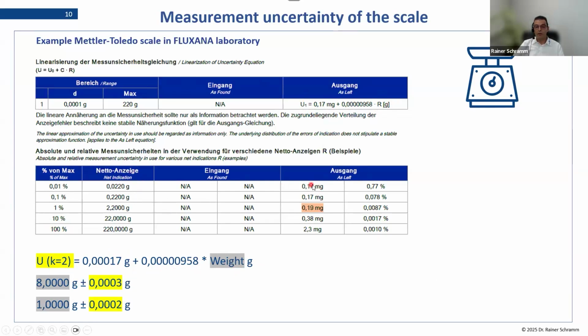From very small weights, it's always 0.17 milligram. And then for higher weights, an additional error is added. And for our flux weights, like 8 gram, this will be in the range of 0.3 milligram, or for a 1 gram sample, it will be in the range of 0.2 milligram, so very low. So this is probably not the error you will see in your laboratory. That means if the balance is installed under optimal conditions, then the weighing error is really small.